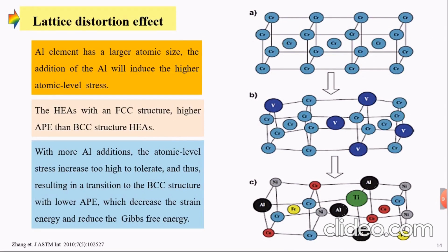The most important effect is the lattice distortion effect. Why? For example, if you have a system with small atoms and you add a big atom like aluminum, what will happen? As you add more aluminum atoms, the atomic strain increases too high. So the system has to reduce the energy. In this case, as we saw in the previous alloy, the structure will change from FCC to BCC. Why? To decrease the Gibbs free energy.